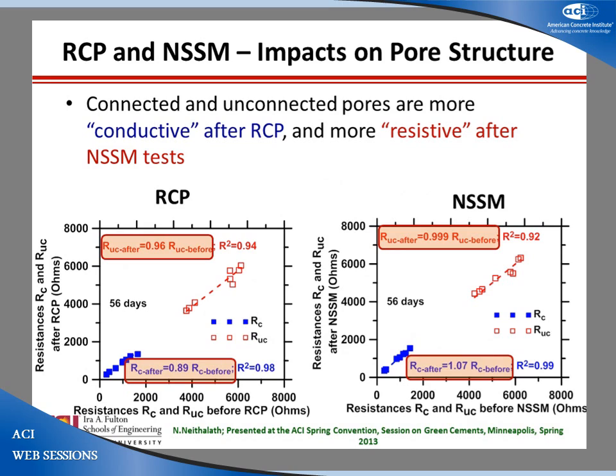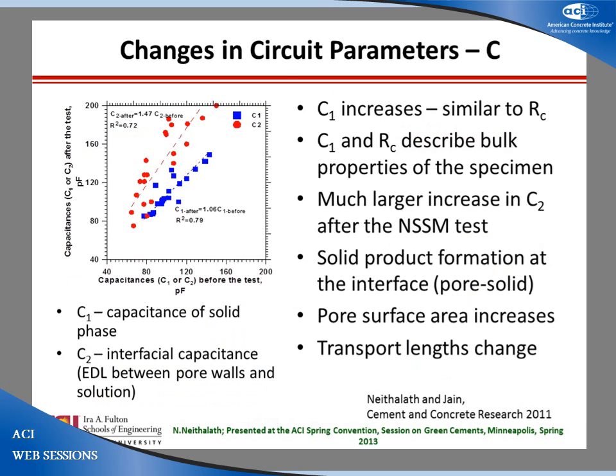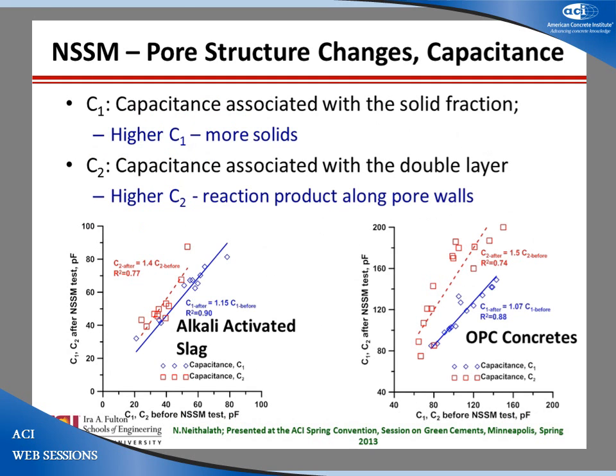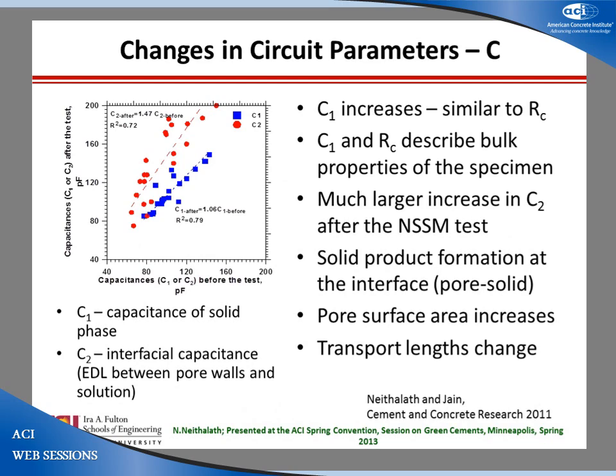You have much longer term for migration test that is slowly starting to change the characteristic of the pore structure, especially in the systems, as I told earlier, because the pore sizes are much smaller. Now, capacitance also are interesting because if you start to track capacitance and how capacitance has changed with time, you can look at understanding the solid product formation at the interfaces. So you can see this is capacitance. This is the interfacial capacitance. You can see that about 50% change in interfacial capacitance.